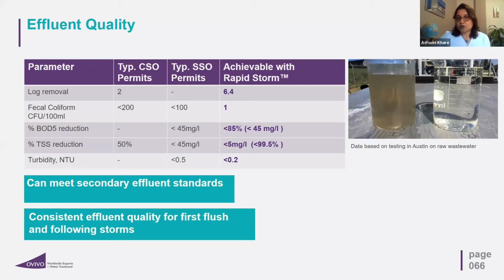6.4. We used raw wastewater, so the fecal counts were in the range of 7 to 10 million. From there, we got to an average of 1. BOD and TSS, the same, greater than 85% BOD reduction. And TSS for membranes is basically anything that doesn't pass through the membrane, so that can be assured to be less than 5 milligrams per liter. And turbidity was less than 0.2. So definitely the system can meet at least the secondary effluent standards.